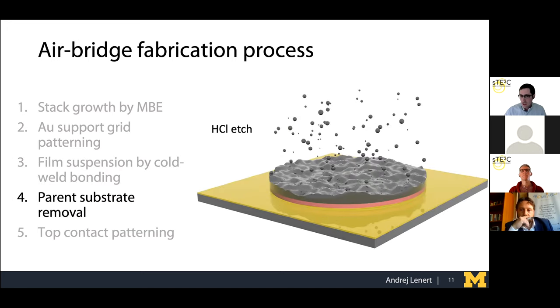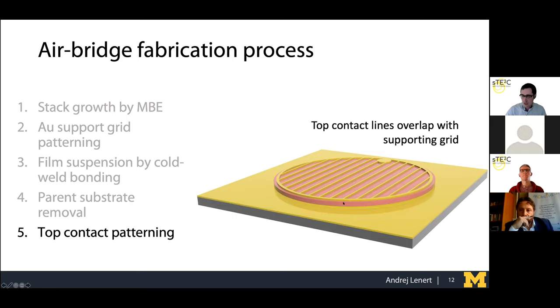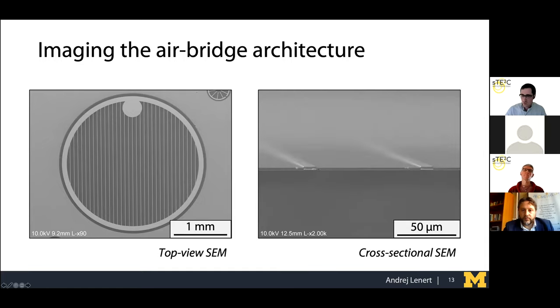After that, we etch away the growth substrate, the indium phosphide substrate, leaving behind the absorber and the TPV cell. So this is the epi film that's left behind. And then we pattern out the area and put down top grids. So it's a pretty simple process if you look at it. But remarkably, we're able to preserve the air that's basically trapped during that wafer bonding step. And so this is the silicon handle. These are SEM images showing the top of the epi film, top of the contact line, and the air gap that we were able to achieve.